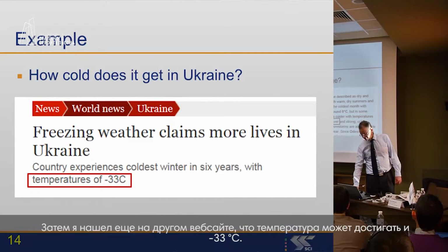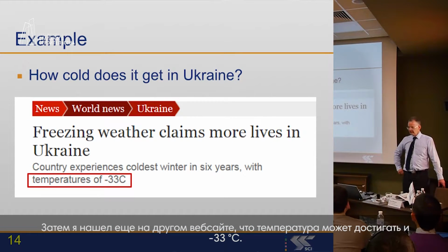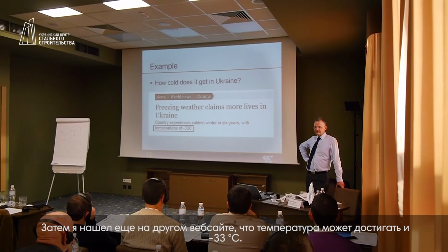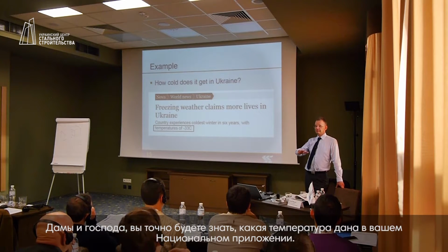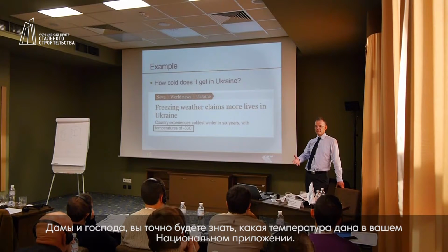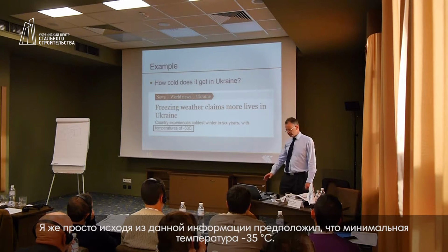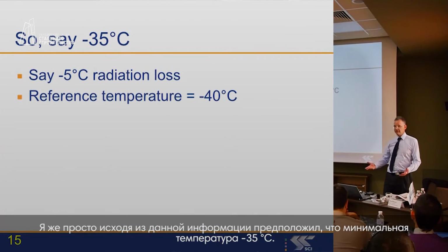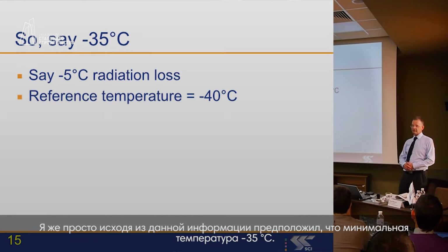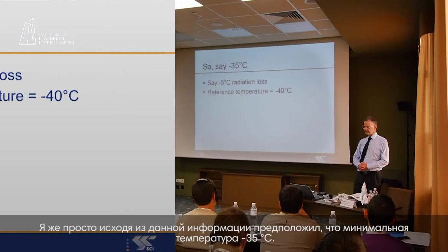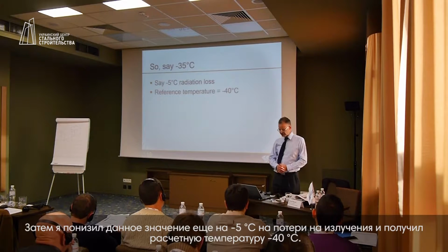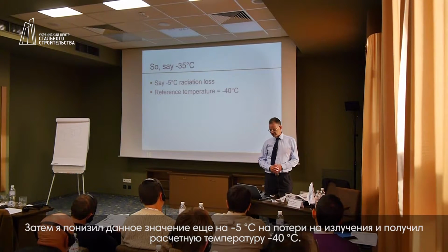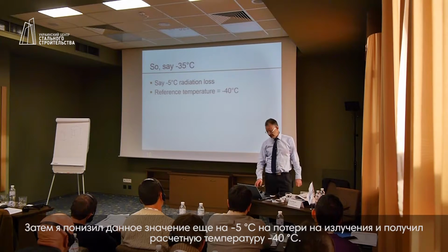But then I found another website, and that said -33. Ladies and gentlemen, you will know, maybe your national annex has some data. I have assumed for this example that maybe the coldest temperature is -35. You will know better than me. And then I have reduced that by 5 degrees for a radiation loss, so my reference temperature is -40.